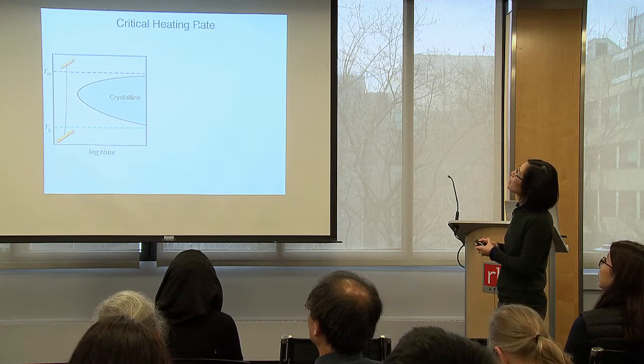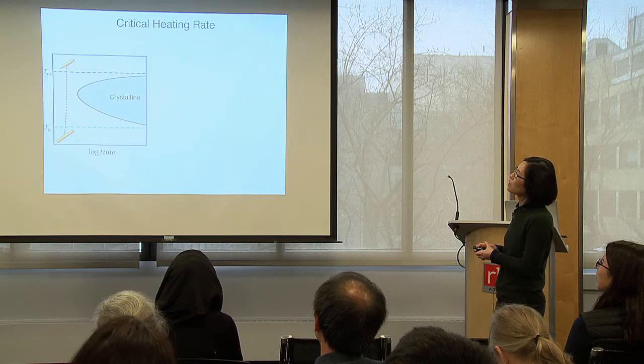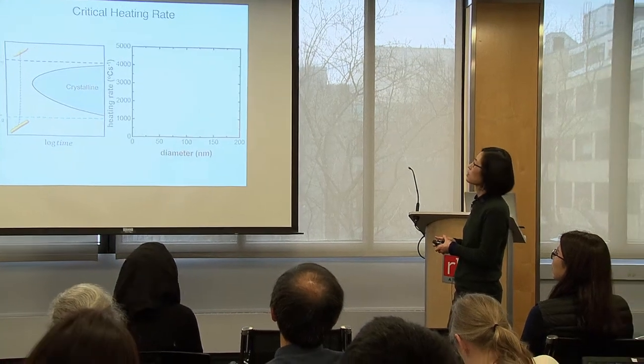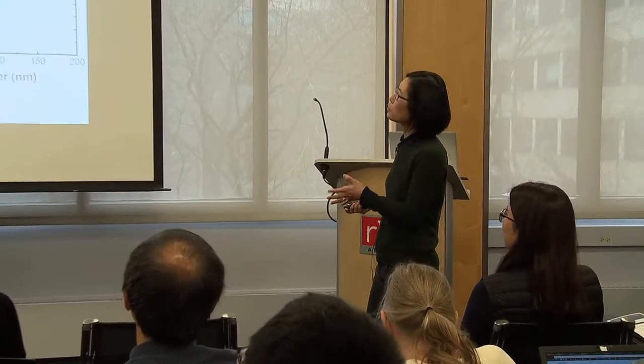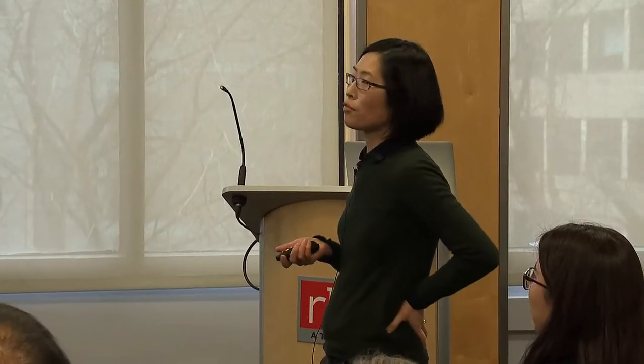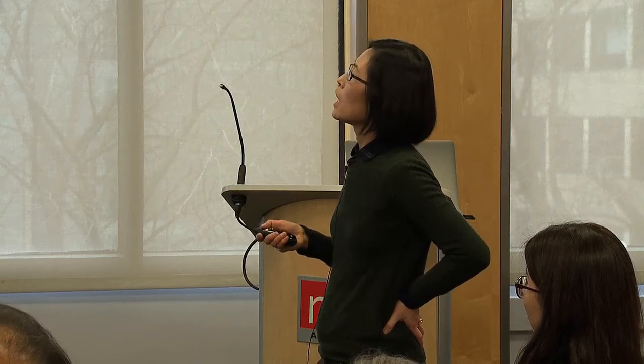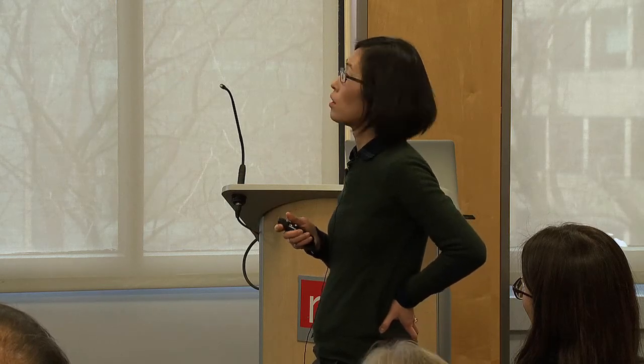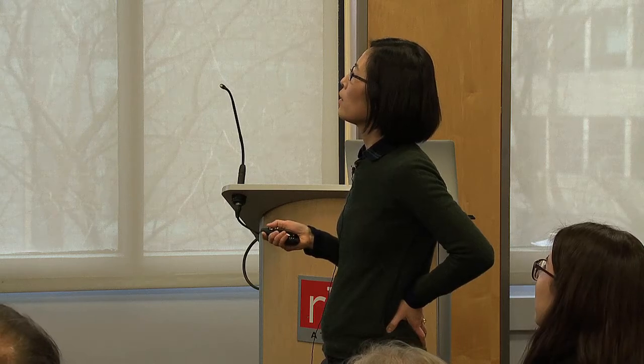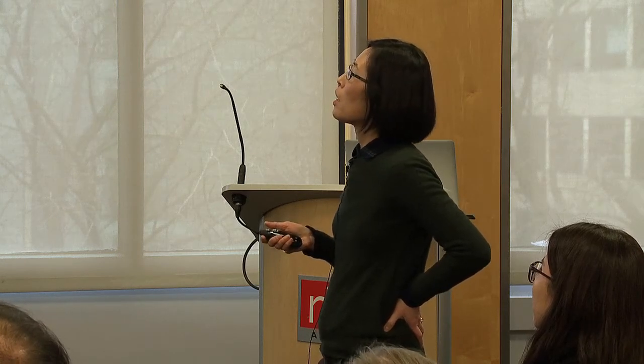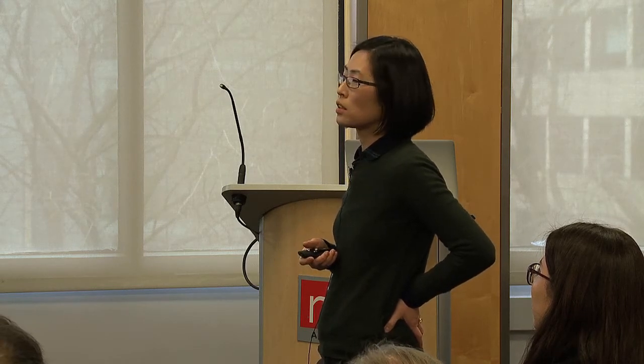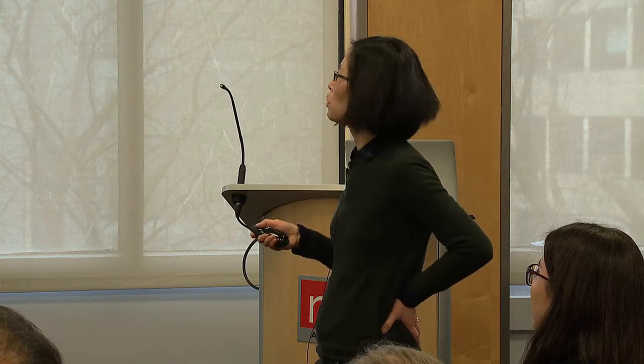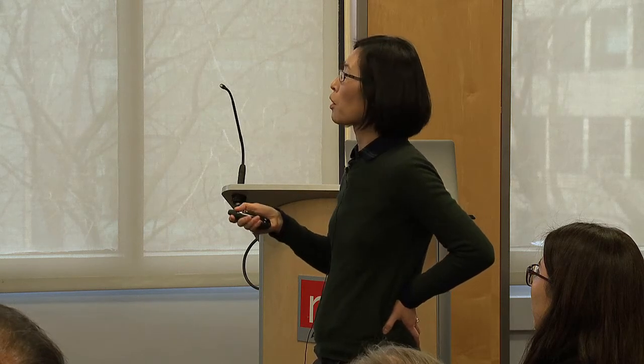So heating rate. Okay, so if you heat the glass really fast, it's just going to become liquid, bypass the crystalline part. You can imagine doing this in experiments where I just heat it really fast using, again, the Protochips holder. If I don't see any crystallization events, either by diffraction peaks or intensity contrast, maybe I mark it as a circle. If I heat it slowly, then I'm going to see some crystalline events. Right at the nose is the critical heating rates. So maybe sometimes you see a crystalline event, other times maybe you don't see it. So you do it many times right here to sort of mark where your nose is.